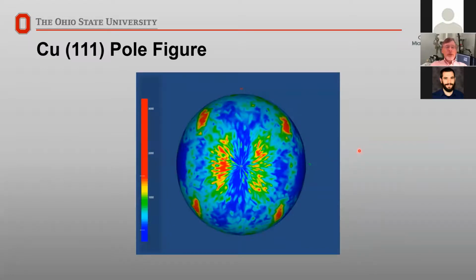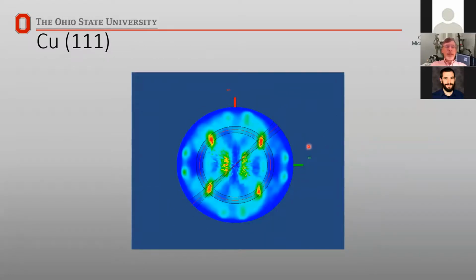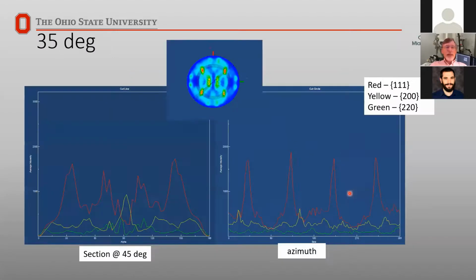So if we take this information, and this is a slightly different contrast ratio, I can take a section across this pattern. So this would be slicing through the upper hemisphere, or I can take one particular latitude in that hemisphere and look at the distribution around that. So if I start doing that now, if I go 35 degrees up from the equator, I find that my 111 planes are showing every 90 degrees. I've got a lot of 111 planes, and those are my body diagonals.